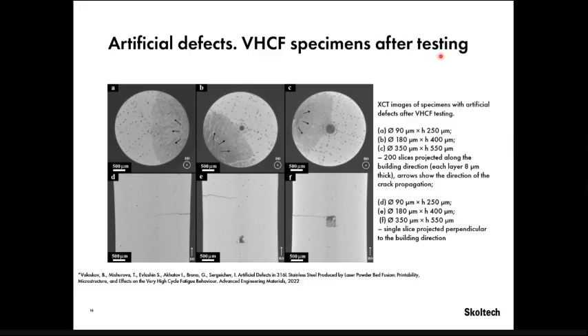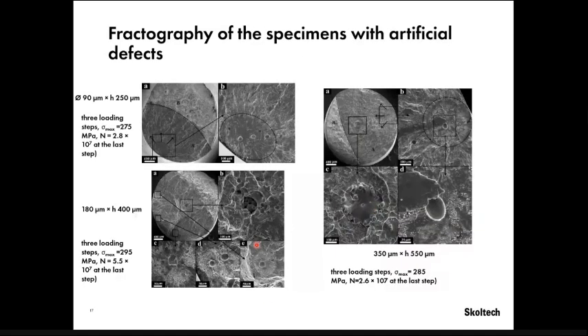and after this testing, the specimen is not divided into two parts, so we can check the crack in the X-ray computed tomography, and we found that the cracks didn't start from the central artificial defect. And we also supported it by fractography. So despite that we have such large artificial defects in the very center of the specimens, the crack starts from some pores which are process-induced, I mean, additive manufacturing process-induced defects. And it was for all specimens.